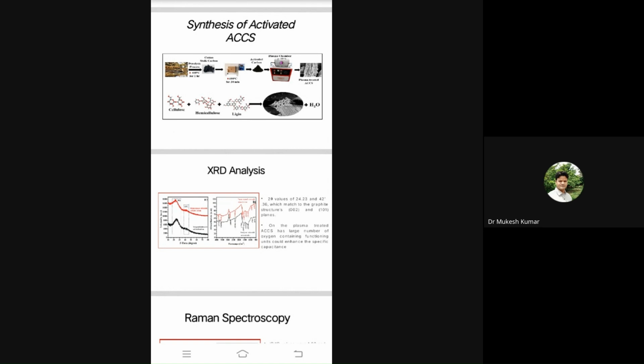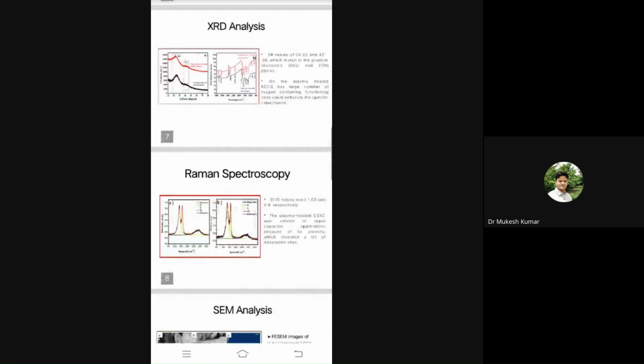Next we see the XRD analysis before the plasma treatment and after the plasma treatment. In the XRD analysis, the two theta values are 24 degrees and 42 degrees, which match the graphite structure, and the planes are 002 and 101. The plasma treated activated carbon has a large number of oxygen containing functional units to enhance the specific capacitance. These results are seen in the FTIR analysis.